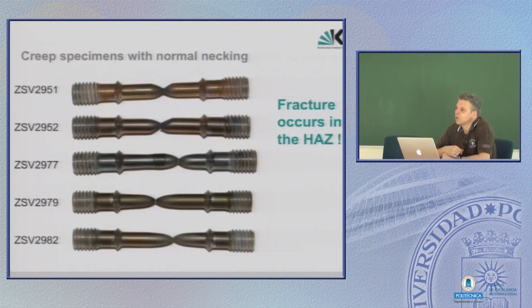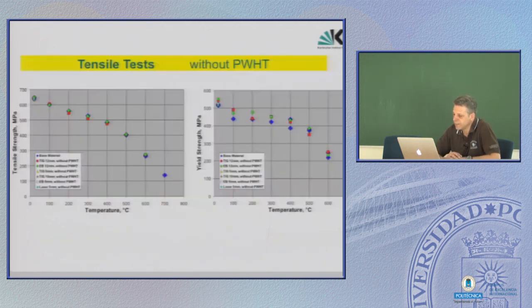The fracture never occurred in the weld. It always started where the material is very fine-grained, and if you remember, a fine-grained material delivers the worst creep properties, and that's why all this necking and finally breaking of the specimen occurred outside of the weld, but not completely outside, right in the vicinity of the weld, that's in the heat affected zone. This is the weak point of Eurofer welds under creep load. Tensile test, that's the same, and this is an overview of several hundred welds, very concise and very simple to interpret.